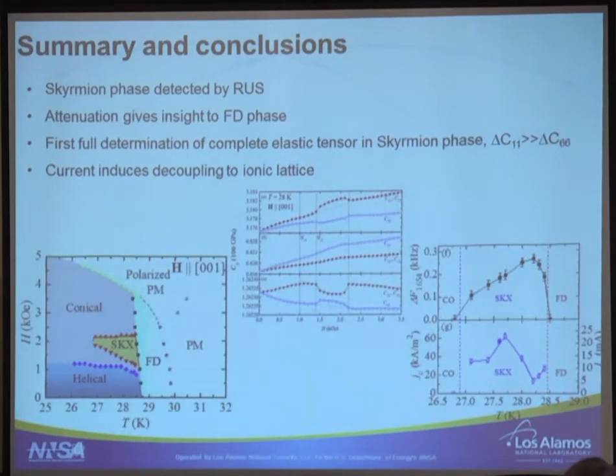Anyhow, to summarize, we can see skyrmions, we can determine the elastic constant, and we can determine the changes that they make to the elastic constant. We can also see inside the fluctuation dynamics, which I didn't have time to go through today. The changes in delta of C11 are much bigger than those of C66, and we can also induce decoupling with critical current and study temperature.